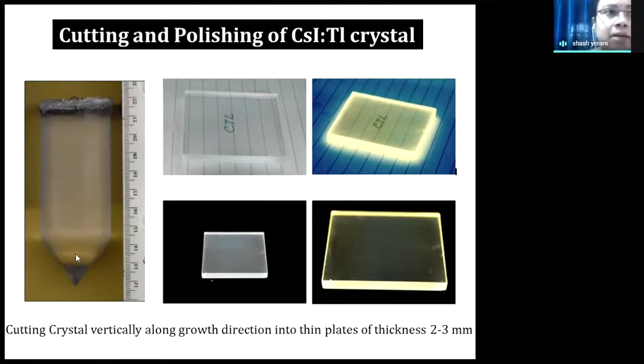Cesium iodide single crystal is grown by a method called the Bridgman single crystal growth technique. Here we melt the cesium iodide polycrystalline material, and then very slowly cool it. This is a 50 mm diameter and around 100 mm length crystal. From this crystal we now have to take out a part. This is a square part which we have taken out.